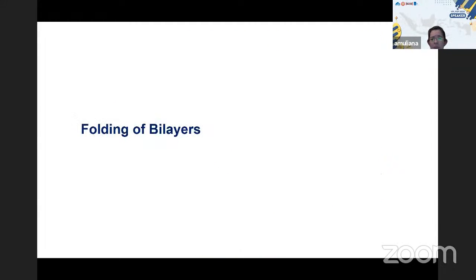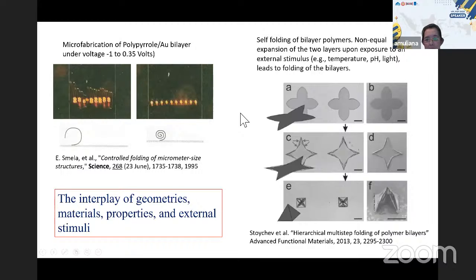So with that, my final example is actually how we want to capture the bilayers of the polymer folding, right? So the idea of this is for microfabrication, and I'm showing you these two articles, which I think are interesting. The first one is actually the combination bilayer out of polymer and gold. So the activation here is through voltage or electric field. Because of a significantly different response between the two layers, through the electric field activation, you can achieve all these folded shapes, right?